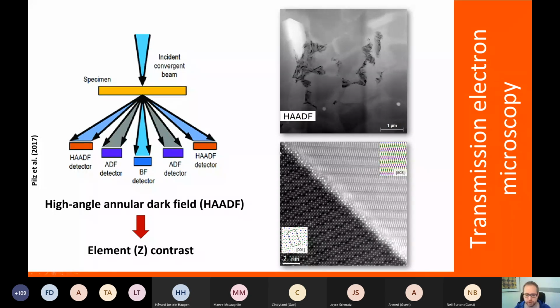I won't go into much detail again here, but you can do high angle annular dark field imaging at atomic resolution. And this is quite an impressive image of a phase boundary between two materials. All these little dots here are, simply speaking, atom columns. And you see that the contrast of these columns varies, which is the direct representation of different elements within this material.